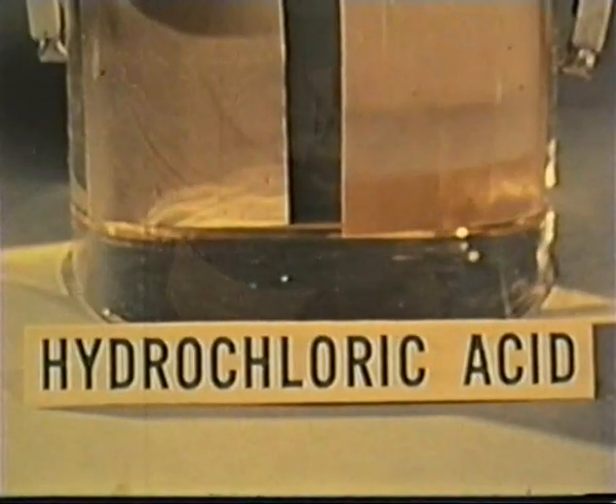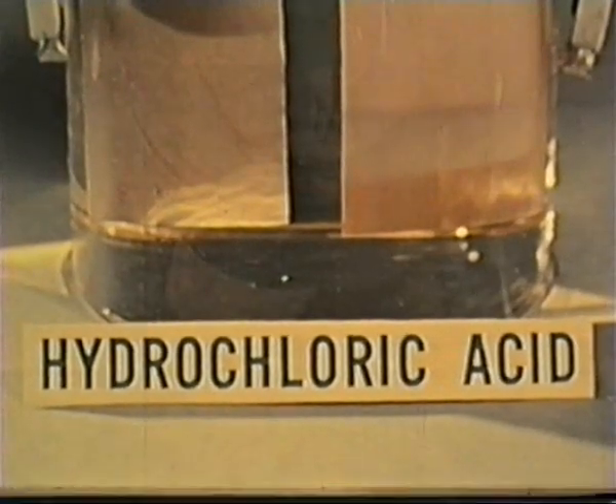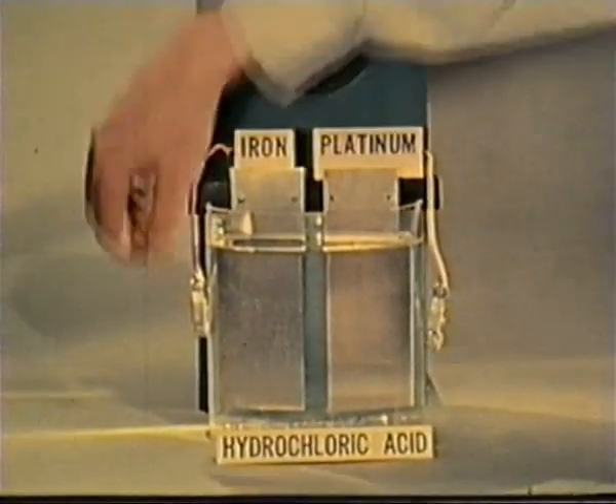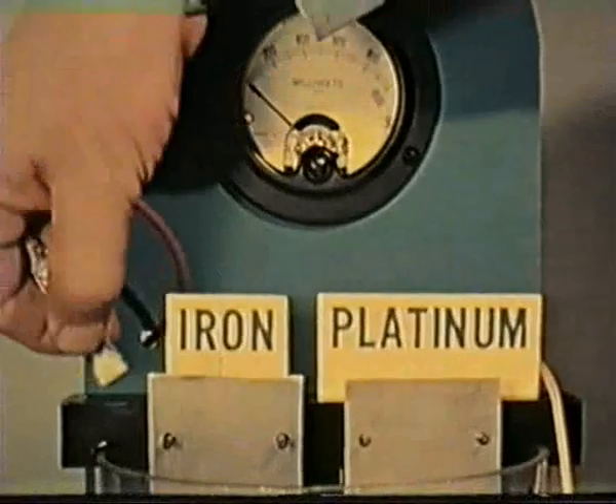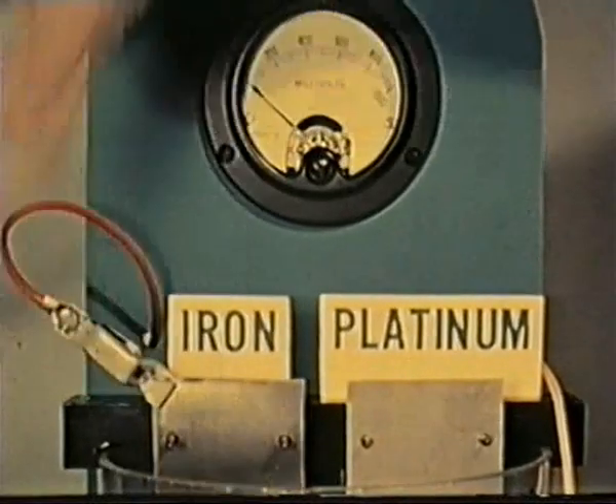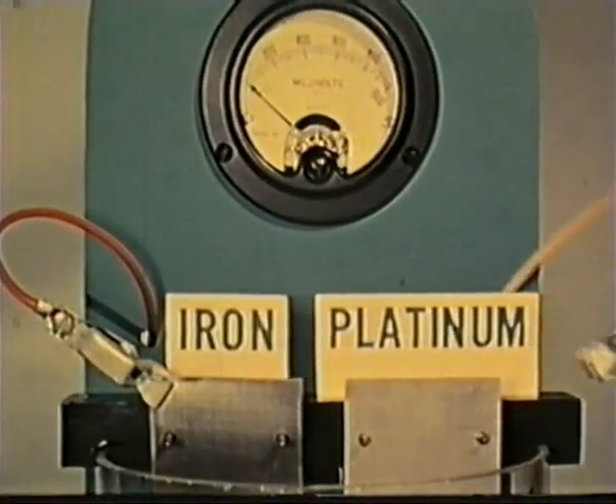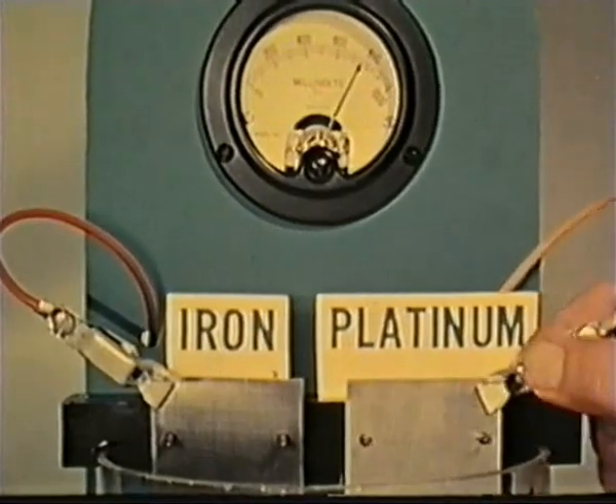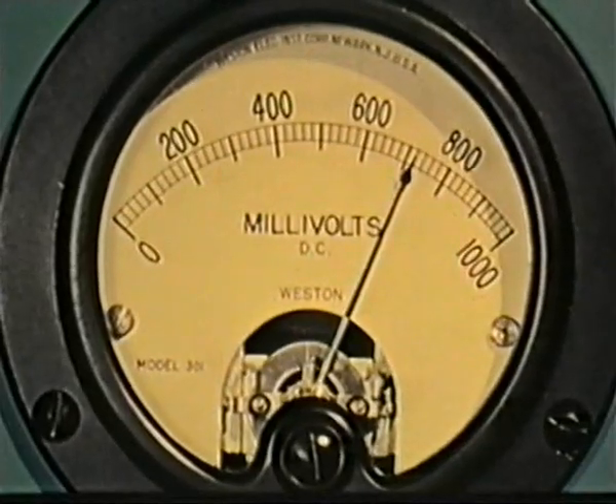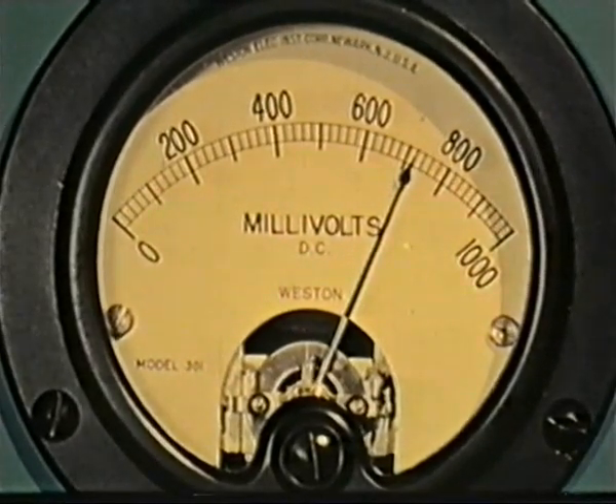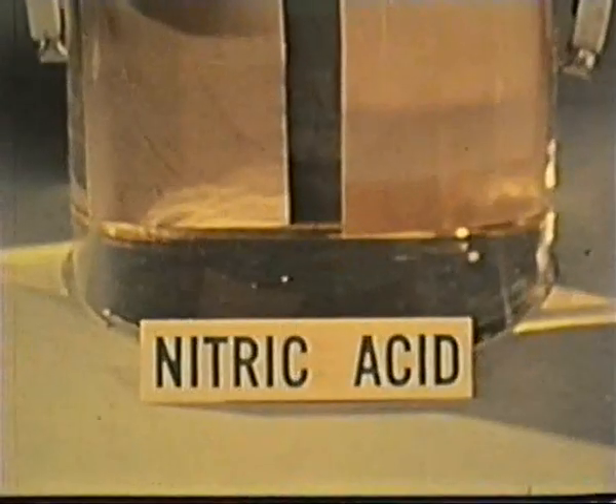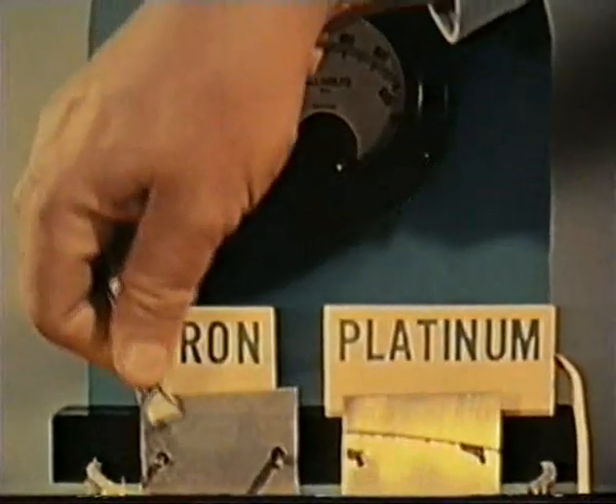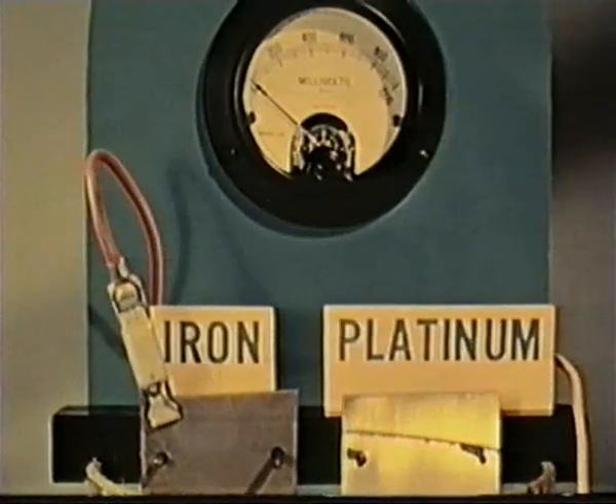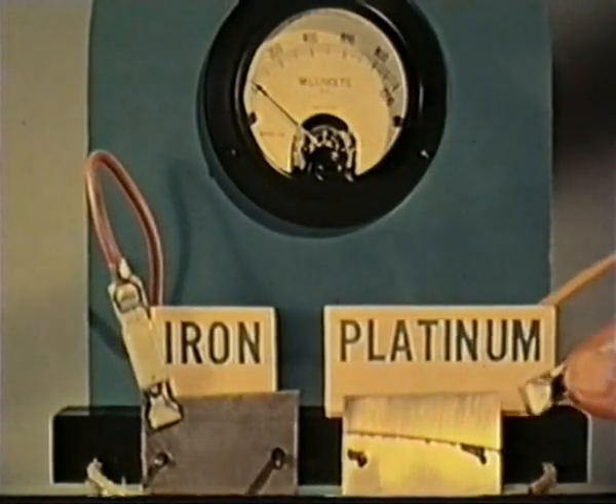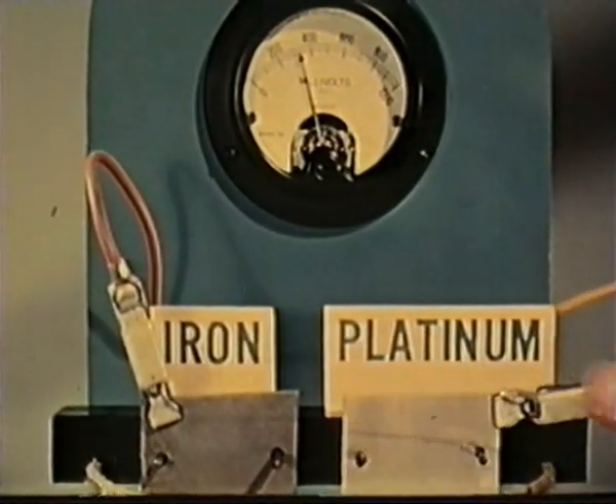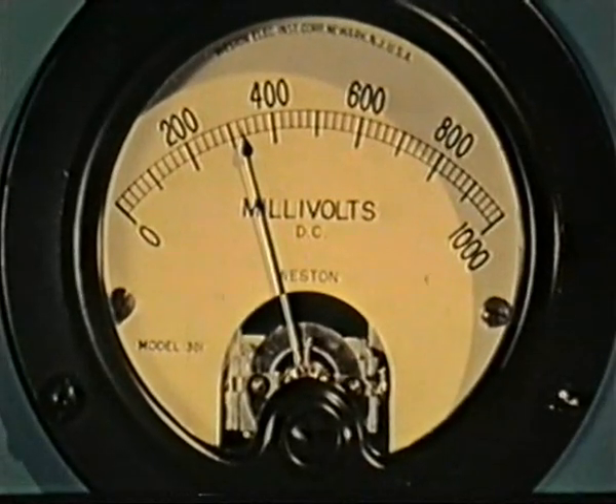Iron is active in hydrochloric acid. When we couple it galvanically to platinum and then measure the potential difference in hydrochloric acid, we find this potential to be about 700 millivolts. But if concentrated nitric acid, in which iron becomes passive, is substituted for hydrochloric acid, we find that the potential difference between iron and platinum has decreased to about 300 millivolts. However, the frail film responsible for the passivity of iron in this case is easily damaged.